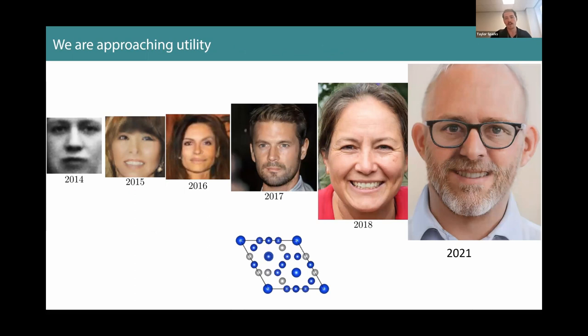Well, first off, where are we at? I think that we're sort of like here. In the world of generative models for inorganic materials anyways, we're way better than our first work. It's getting to the point where it's interesting enough that you might want to be doing something with this crystal. I presented this at the Gordon Conference a couple months ago, and there's a couple of solid state chemists right then in the room that saw one of these and thought it was interesting enough that they actually phoned home to their postdoc who had it made. And by that night at dinner, I had two groups telling, a group in Germany and Tyrell McQueen's group at Johns Hopkins had both made these things and said, you know, by golly, it was the right crystal structure, right unit cell. The atoms were not in the right spots, but it was an interesting enough thing that it tempted some of them to try and make it.